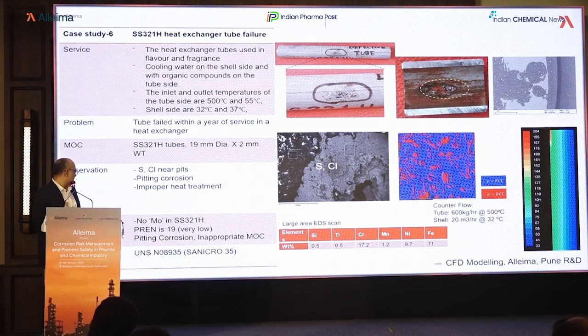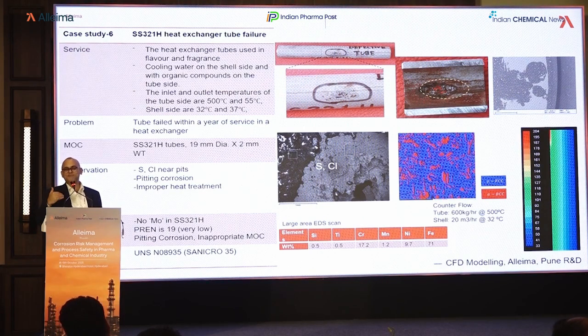And then here the grade was 321, so it doesn't have moly. And if you don't have moly, then your PREN number will be further down, 20. It has 19. So if it had come to us initially, we could have easily told that this will not work. But the customer faced a serious issue with this, and they wanted this sample to be investigated.